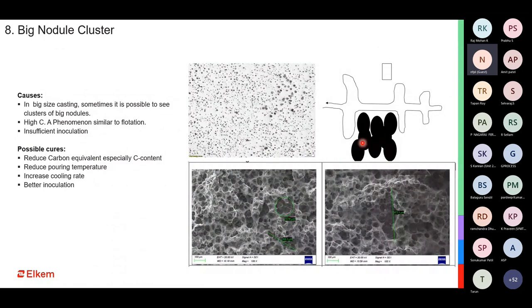Again, the next one, big nodule cluster. This again is a continuum. This is also a problem which is caused by high carbon equivalent for a given section and poor inoculation. If you look at this particular photograph, this gives you the actual way how the casting solidification happens. So this is the dendrite, right?